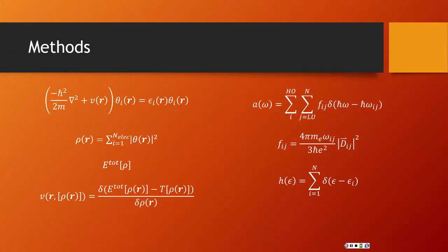So you're saying it's because... you probably were on the right track. I didn't really catch what exactly you're trying to say. So I was pointing towards the oscillator strength. So what happens with oscillator strength? It depends on the dipole moment and the dipole moment matrix elements, and if those are forbidden, then these low transitions, HOMO-LUMO transitions, are not optically active.